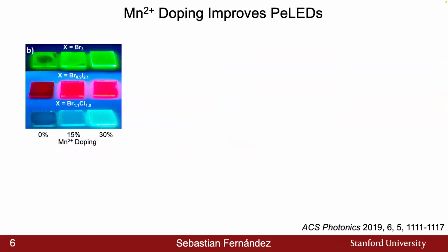And so that brings us to the first section, in which the Congreve Lab in the Rowland Institute at Harvard first looked at what if we replace a certain percentage of the lead with manganese. What they saw was that across green, red, and sky blue thin films, up to a 30% replacement with manganese dopants actually improves both the brightness and the uniformity of the thin film.